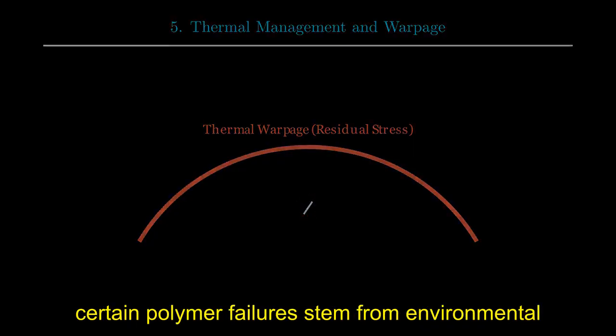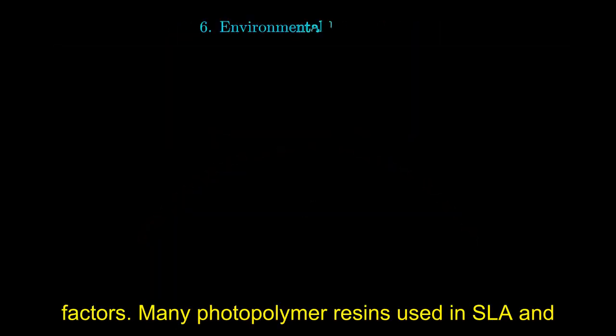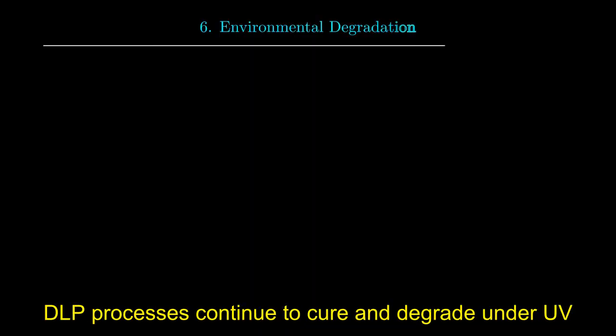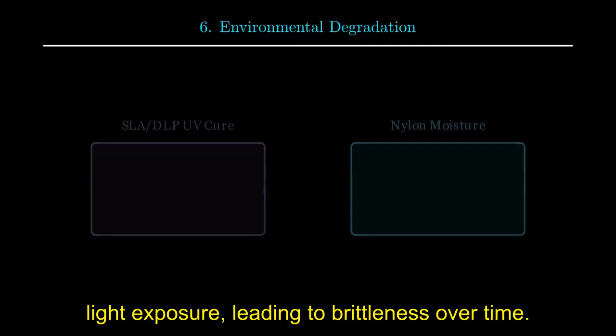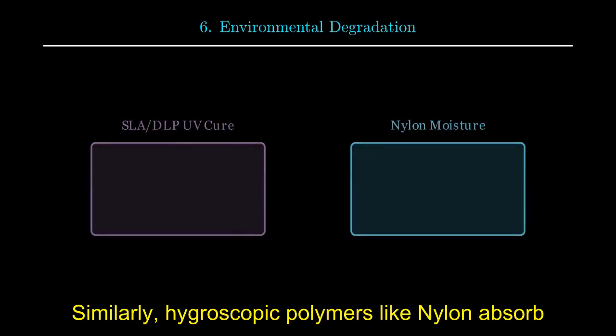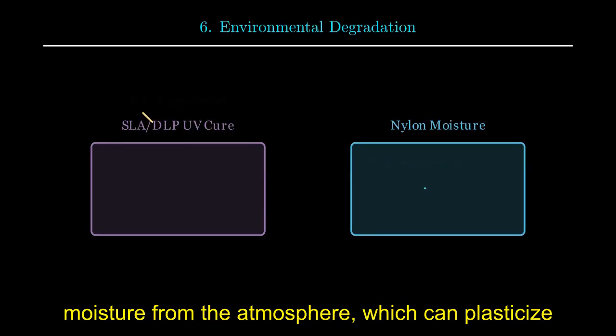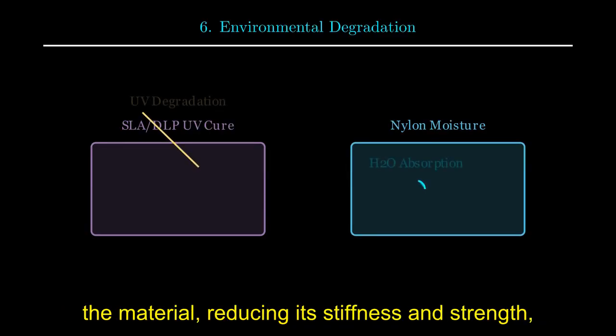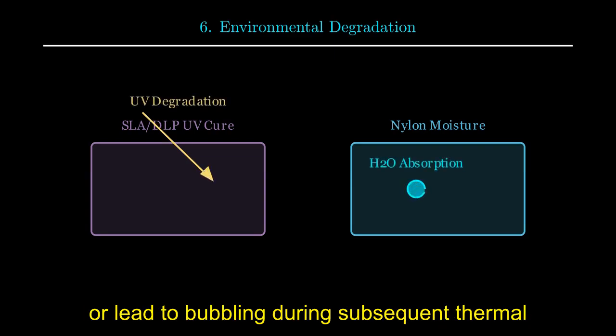Furthermore, certain polymer failures stem from environmental factors. Many photopolymer resins used in SLA and DLP processes continue to cure and degrade under UV light exposure, leading to brittleness over time. Similarly, hygroscopic polymers like nylon absorb moisture from the atmosphere, which can plasticize the material, reducing its stiffness and strength, or lead to bubbling during subsequent thermal processing.